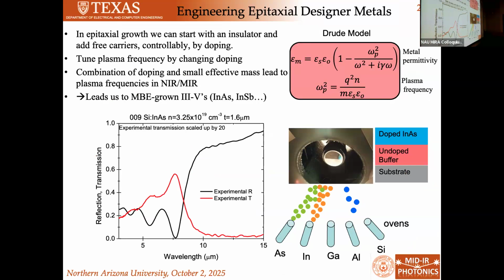This is a picture of a half wafer in our chamber, right? We basically have these ovens. We heat the ovens up, we open them up, and there's a molecular beam that carries the elements to the surface, and they arrange themselves atomic layer by atomic layer. So we can grow these materials, and then we can dope them with, in this case, silicon, which provides free carriers into the system, right? And when we do that, for instance, on a layer of indium arsenide,